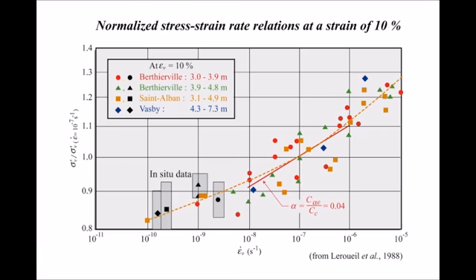Now, the effective stresses have been plotted in a normalized form here, and we have the rectangulars here for in situ data, and the other points are laboratory data, which is indicating that the in situ behavior is in the continuity or consistent with the laboratory data, and indicating that hypothesis B is the correct one.